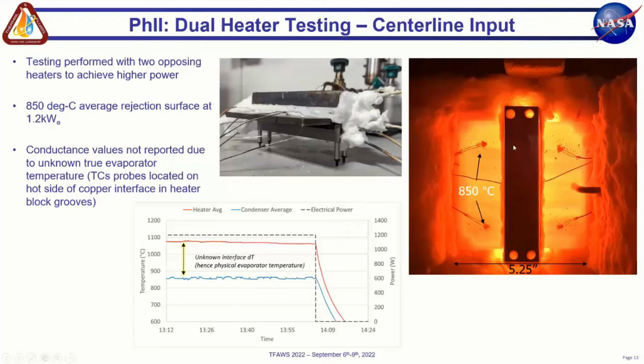One asterisk on this testing is, we don't actually truly know the physical evaporator temperature, as the thermocouple probes are embedded essentially on the hot side of the thermal interface, adjacent to the cartridge heater. So we know the heater temperature and we know the OHP condenser temperature, but the delta there includes a series thermal resistance from that thermal interface.